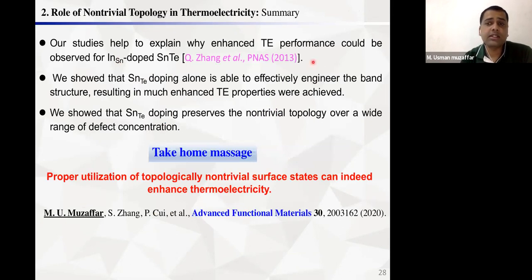So this is the summary of this project. In this paper we try to explain why enhanced thermoelectric performance is observed in the indium-doped SnTe system. Next we show that indium doping alone is able to effectively engineer the band structure, resulting in much enhanced thermoelectric performance. Moreover, the SnTe indium doping preserves the non-trivial topology. So this is the take-home message: a proper utilization of the non-trivial topology surface state can indeed enhance the thermoelectricity. Thank you.